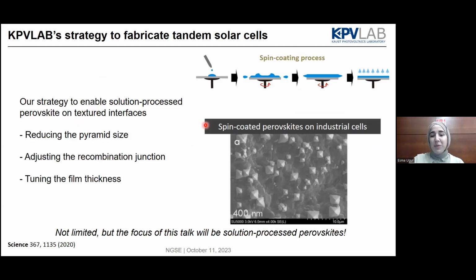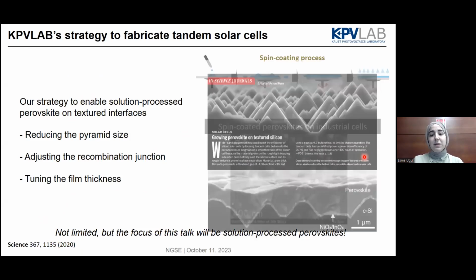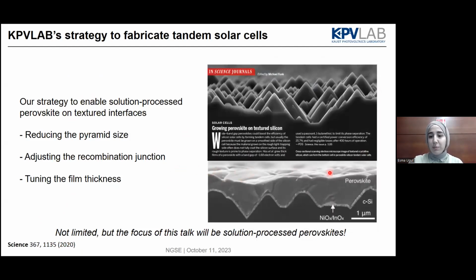But maybe most of you know that in the perovskite-silicon tandem field, our approach in the KPV lab is solution-processed perovskite thin films on textured surfaces. In 2020, there was a nice paper from a group that managed to spin coat the perovskite on textured silicon wafers, allowing full coverage of the perovskite film, by reducing the pyramid size, tuning the pyramids of the silicon so that you can still benefit from the silicon's response, and also adjusting the recombination junction and the film thickness.